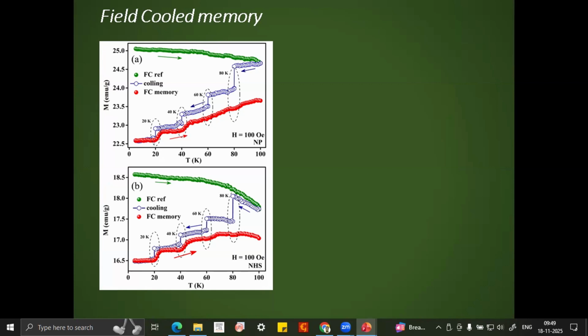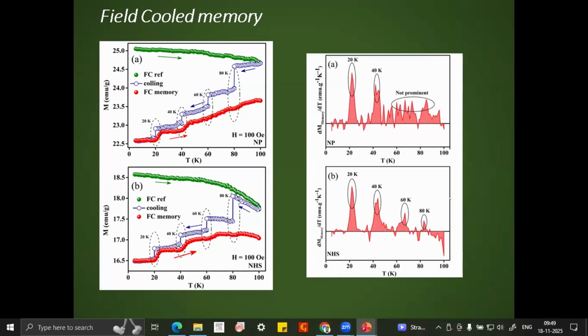If the system, that is the red curve, this is the memory curve, can retain its memory, then it should follow the cooling curve, that is the blue curve. Now you can see that for the nanoparticle, the red curve cannot follow the blue curve very well, but in the hollow sphere the following is much better. Also, I have plotted the derivative curve. You can see that for nanohollowsphere, the four memory peaks are there. On the other hand, only two memory peaks are there at 20 and 40 Kelvin for nanoparticle. So a more prominent FC memory effect is there in nanohollowsphere.